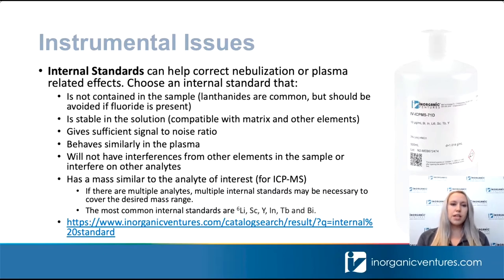Another possible solution is using an internal standard for your analysis. So an internal standard is going to help correct for those nebulization and plasma-related effects. So I just want to go through a couple of considerations for choosing your internal standard. So the first thing you want to make sure is that your internal standard is not contained in the sample. So of course, you want something that will be consistent in concentration in all of your solutions that you're running. So one common option is lanthanides, rare earths. So these are not going to be contained in common samples.